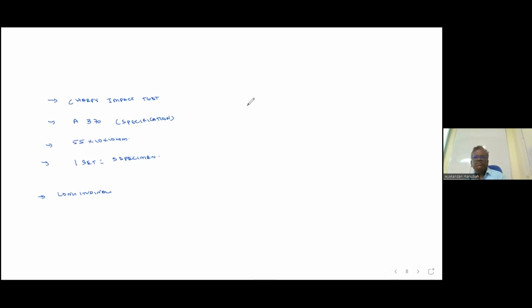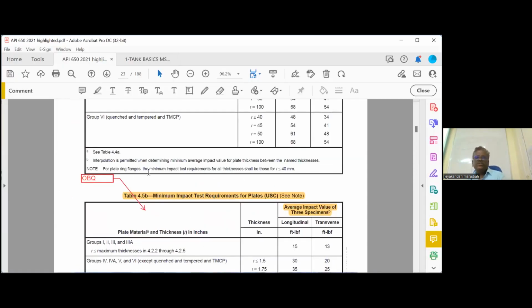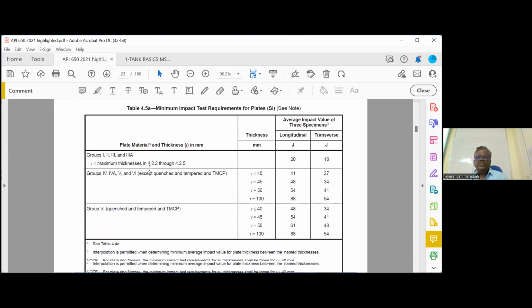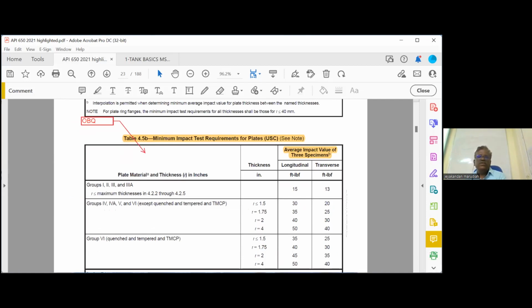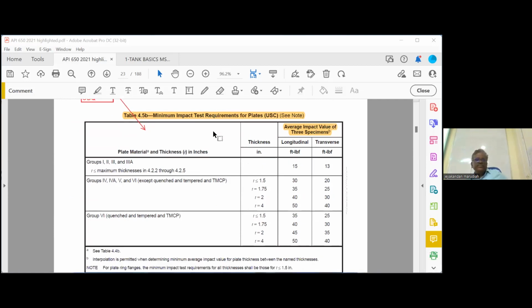Our material is group 5, thickness is 0.5 inch. So what should be the longitudinal specimen value? You can write after that, no problem. See, this table you have to refer to. Again, there will be A, B table, page number 4-13. Tell me what will be the longitudinal specimen for group 5, 0.5 inch. Longitudinal will be 30 foot-pounds. You can see here less than 1.5, group 4, 4A, 5, 6, except quench temper and TMC. Okay, less than 1.5, longitudinal will be 30 foot-pounds.